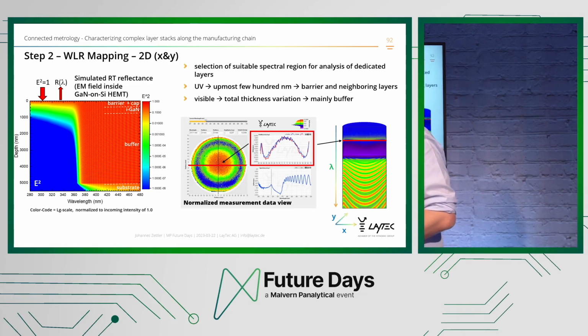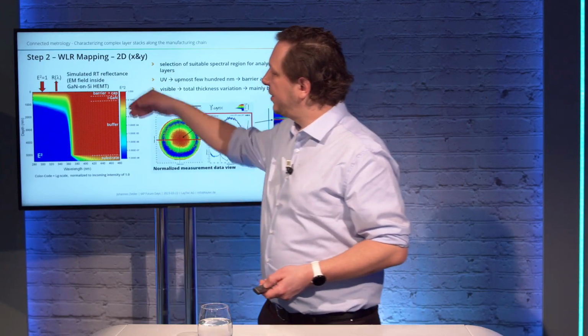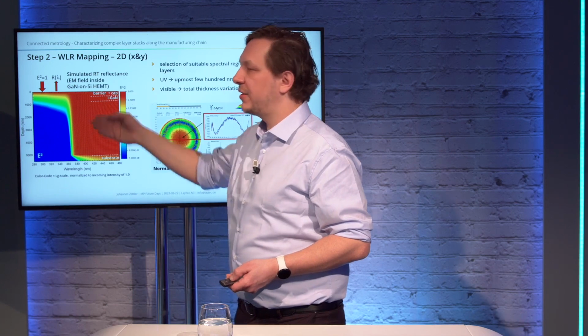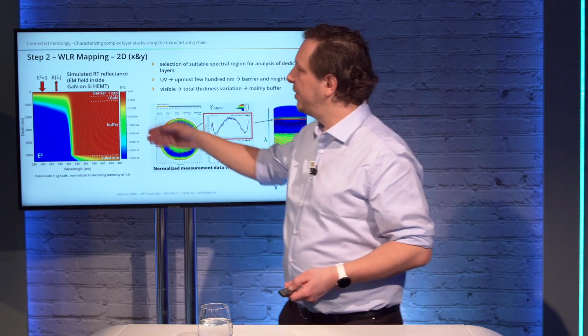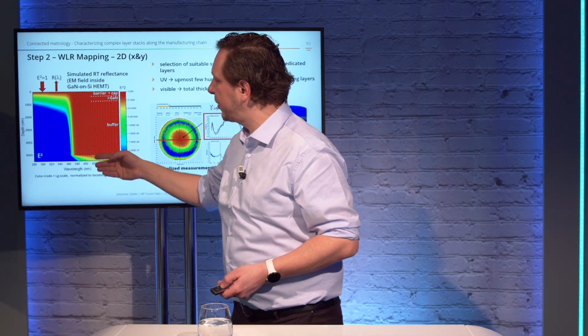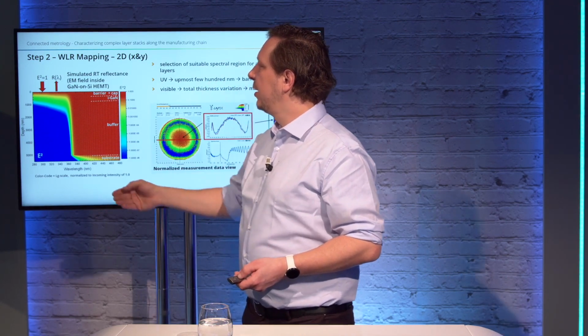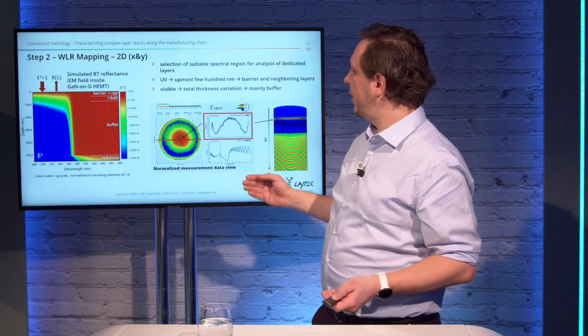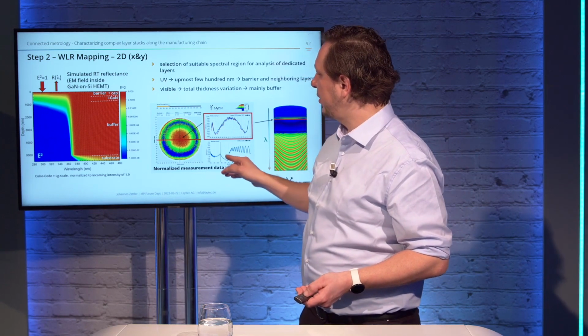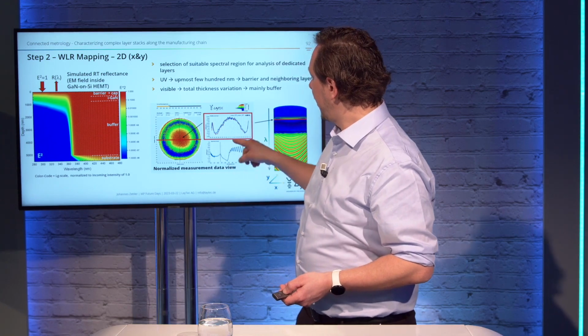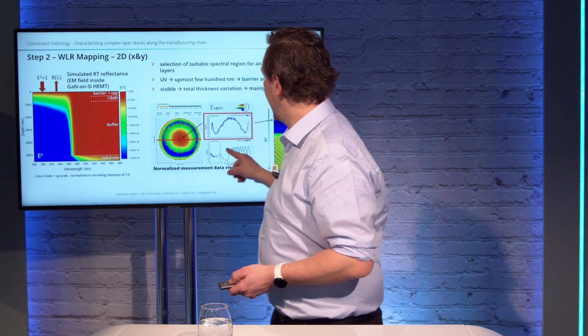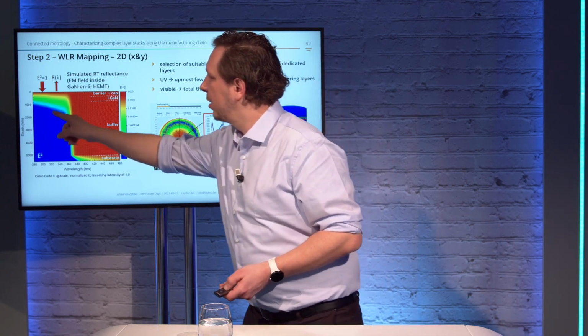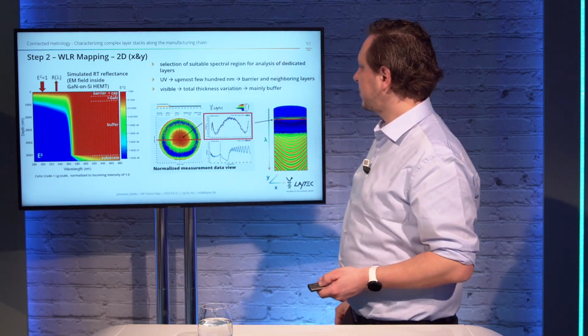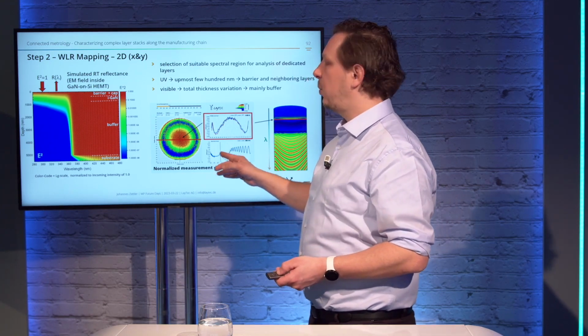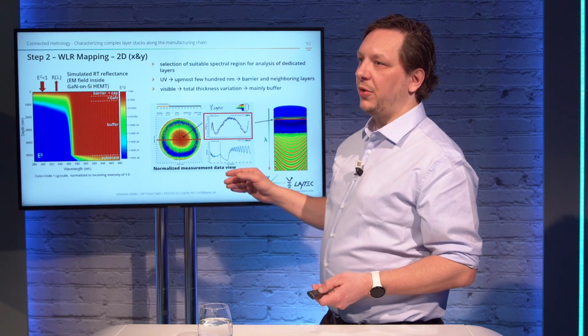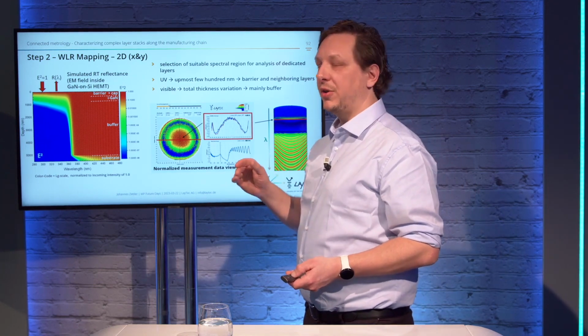Whereas when we go above the band gap, because all of these materials are transparent in this wavelength region, the light penetrates really down to the substrate, and all that we have left here is basically Fabry-Perot oscillations. So we have the spectrum here at the center. The Fabry-Perot oscillations are in this region, and the peak that we see here is in the UV region. Simulations show that this peak correlates very well with the aluminum content in the AlGaN barrier.